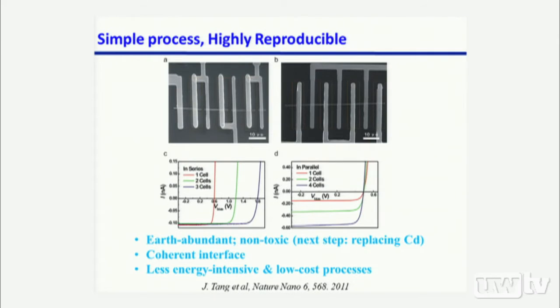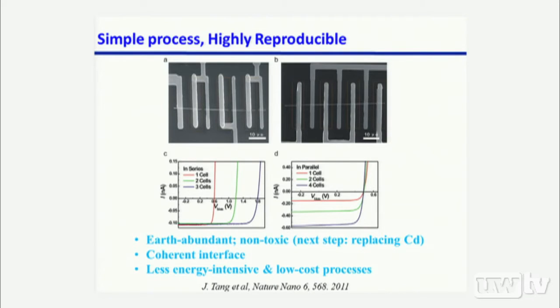And these nanowire solar cells are very reproducible. If you link a couple of these solar cells in series or in parallel, you can see that the performance of the individual devices is very similar. So you can either add up the voltage or add up the photocurrent, depending on how you link them. In many cases, particularly at the single nanowire level, it's fairly hard to make identical devices from wire to wire. This again illustrates that we can utilize earth-abundant element-based materials, utilize very mild chemistry, and create high-quality junctions that give us high fill factor and VOC, and eventually lead to very high energy efficiency that one can push into the market.